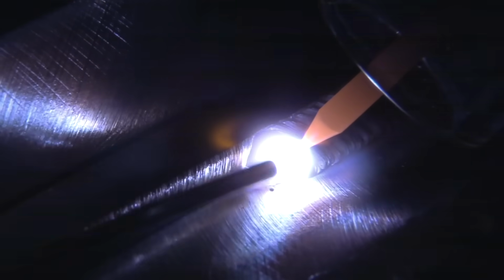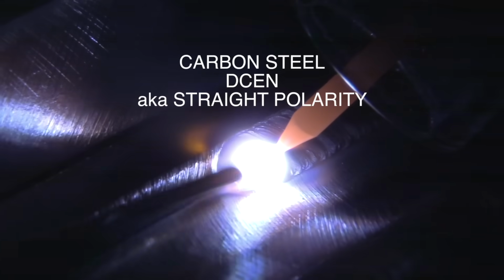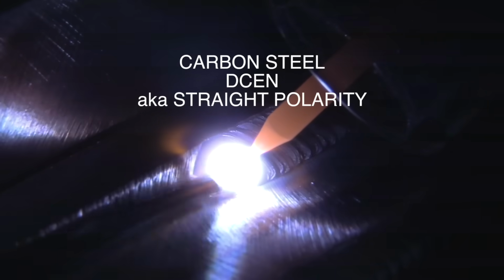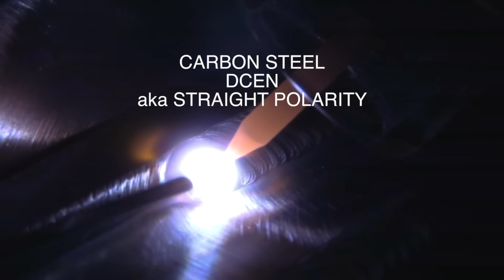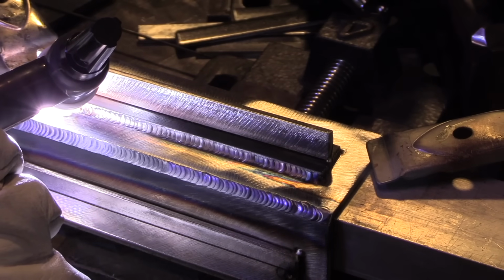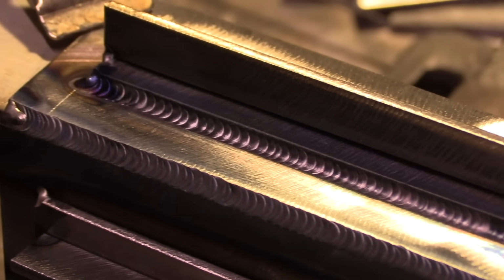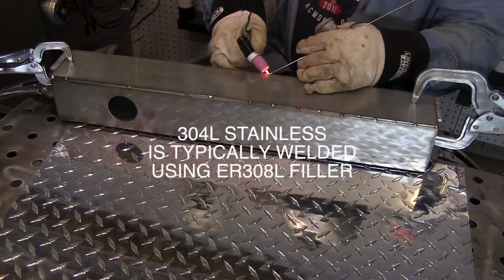Once you've got the metal prepped correctly, use a nice tight arc where the arc length is equal to or less than the electrode diameter. Don't use too much torch angle, and keep the hot tip of that rod shielded with argon gas, and things will go pretty good for you.